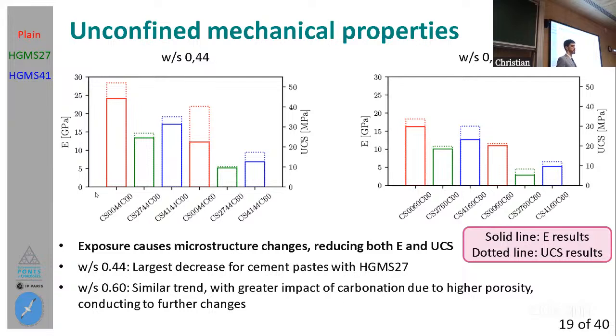So there you will see the results in solid line for the elastic, the Young modulus, sorry. Then you will see in dotted line there the results for the UCS. And then you will see the two groups, water to solid ratio of 0.44, and water to solid ratio of 0.60 on the right. And you will also see that we have a first group of 3 in each of these figures, which corresponds to the C00 samples, which are not carbonated. And then we have the result for the C60 samples, which correspond to the samples carbonated for 60 days.